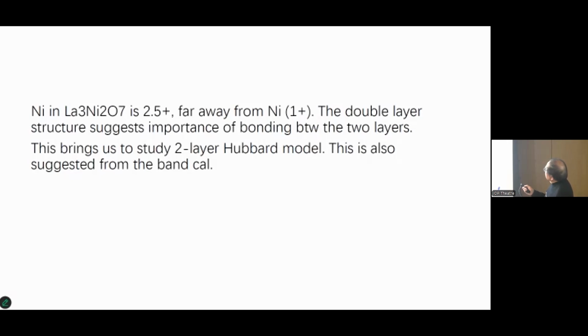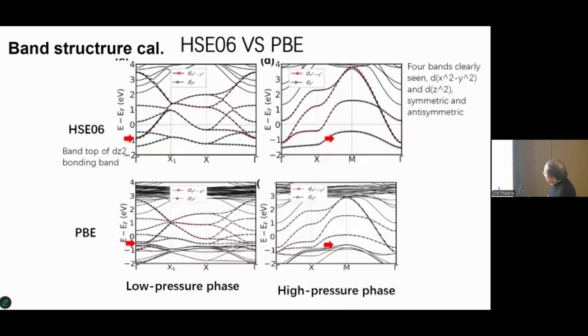So that means it looks very different from cuprate. However, on the other hand, the double layer structure suggests the importance of bonding between the two layers. So that brings us to study the two-layer Hubbard model, which is also suggested from this band calculation. These are two different methods. I think this one is probably a more advanced technique and takes a much longer time.